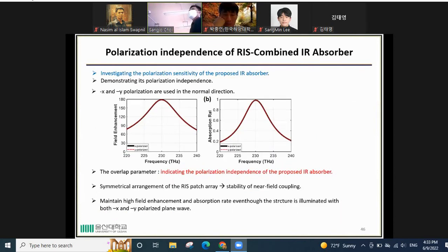We also analyze the polarization independence of the RIS combined infrared absorber. We use X and Y polarized incident waves, which have electric field directions along the X-axis and Y-axis. From this plot, we can see that the S-parameters for X polarized and Y polarized are identical, indicating the polarization independence of the proposed infrared absorber. This is because of the symmetrical arrangement of the patch array, which can generate stable near field coupling.